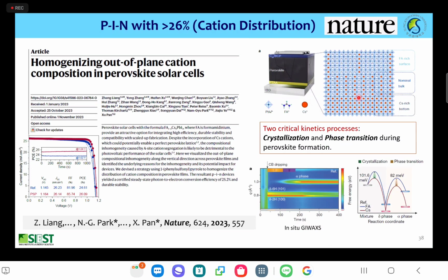So why does this kind of inhomogeneous distribution of the cation happen? This is due to the crystallization, the phase transition kinetics difference depending on the A-site cation, FA cation and cesium cation. There is a huge difference. Therefore, this difference makes an inhomogeneous distribution of the FA cation and cesium cation.